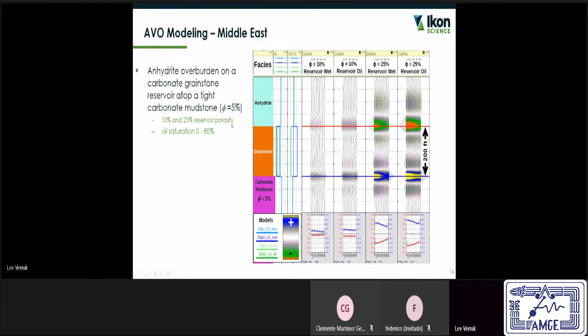And what we observe here in this scenario, which is typical of the Middle East, is we mostly see class 4 AVO responses on both top and base interface of the carbonate reservoir. But the strength of these responses varies quite dramatically depending on whether you have an oil reservoir or a wet reservoir. Even with relatively low porosity, 10%, you still stand a chance of amplitude inversion in terms of the reservoir properties, to see the difference between the wet or water-saturated carbonate and oil-saturated carbonate.